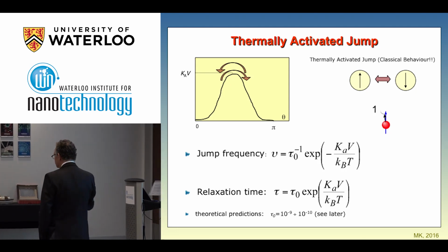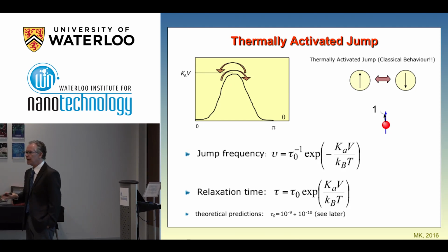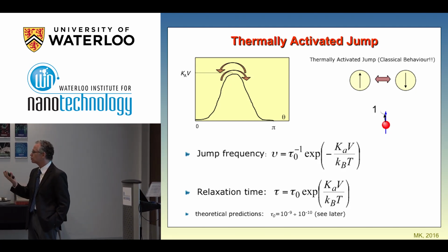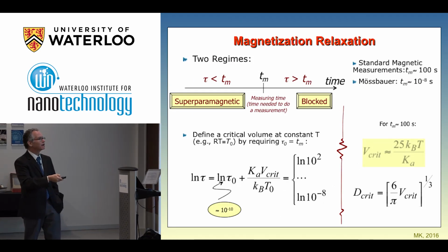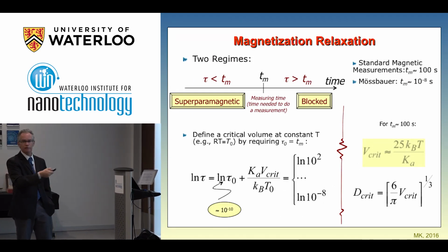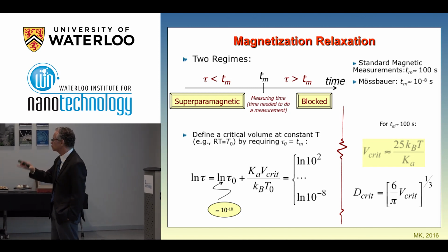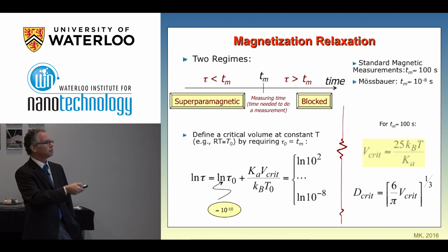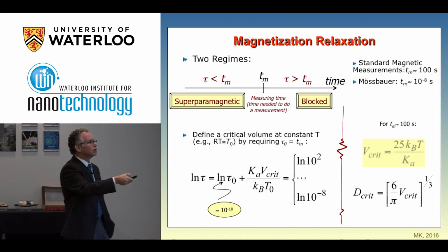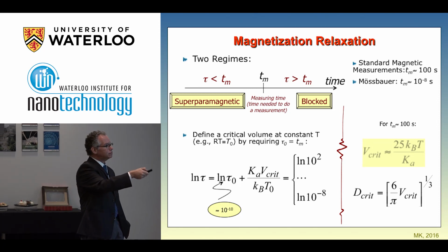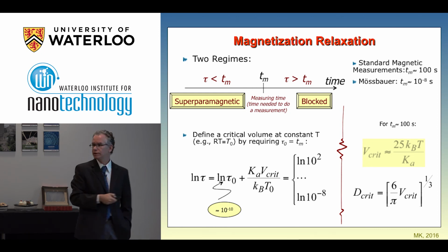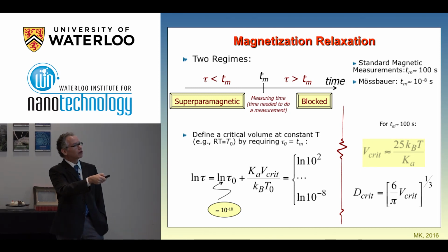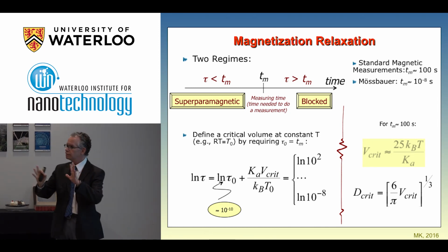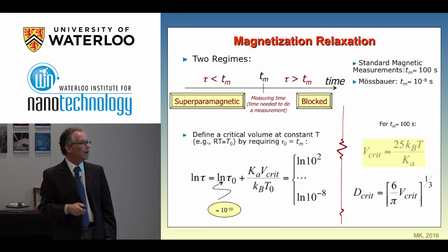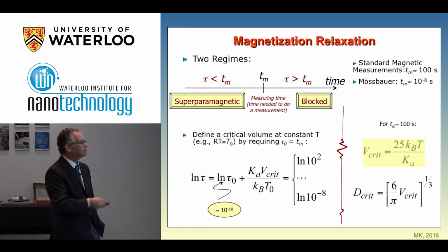And if you wait long enough, any magnetic nanoparticle is considered to be superparamagnetic. Of course, if you're not waiting long enough, if you make a typical magnetic measurement in a SQUID or a VSM or whatever, you use about 1 minute of measurement. So everything that has a relaxation time smaller than the measuring time is considered to be superparamagnetic, and the others are considered to be blocked. Just a definition which is a little bit strange. It depends extremely on the measuring time.